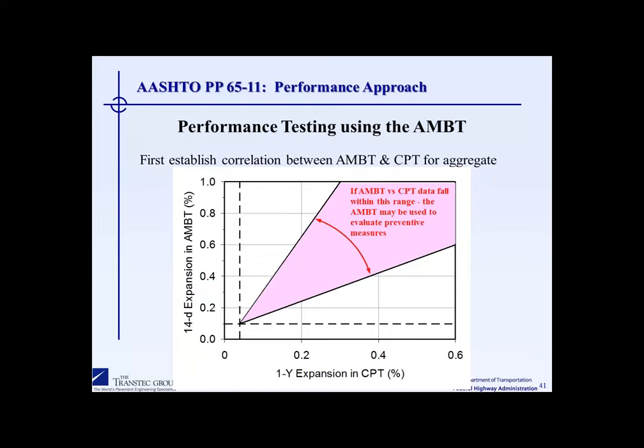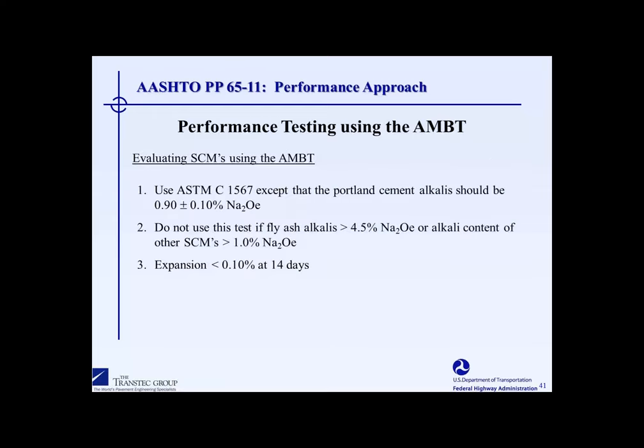As was stated earlier, we strongly recommend that prior to using the accelerated mortar bar test in your local area, one first establishes a reasonable correlation with the concrete prism test. This comes out of the AASHTO PP 65-11. And what this is showing here is the 1 year concrete prism data on the x-axis versus the 14-day mortar bar expansion on the y-axis. And our recommendation here is that provided that your data falls somewhere in this pink band, you're then allowed and able to use this test to evaluate SCMs. I would urge folks that are more interested in this to look for the specific details in the AASHTO recommended practice.